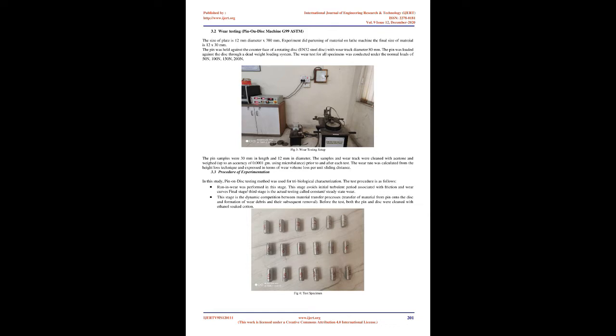Material removal occurred by subsurface crack propagation in a composite transfer layer of aluminum and crushed silicon particles during mild wear, and by subsurface cracking at silicon particles in the highly deformed wear zone during severe wear.